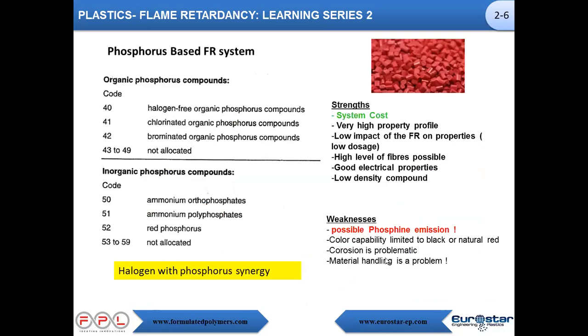Then you say, yes, now with melamine cyanurate we are in the world of enclosures, boxes, connectors. But when you need a stiffer material, a material which is close to the arc, where the fire is, sometimes when you cannot use halogen flame retardant, you can use phosphorus-based material. With phosphorus-based material, you typically have two different systems. The more common one still today is the red phosphorus with an ISO code of 52, and you have organic phosphorus compounds with an ISO code of 40.